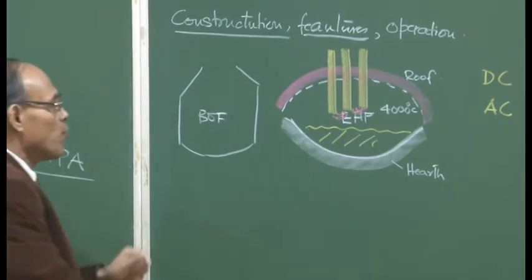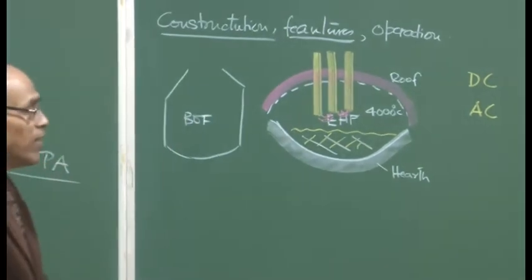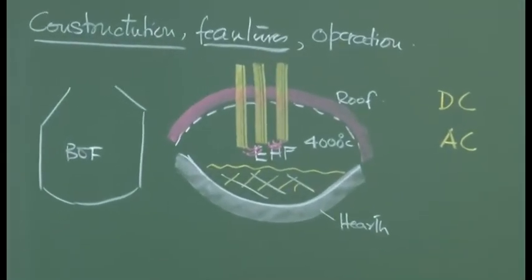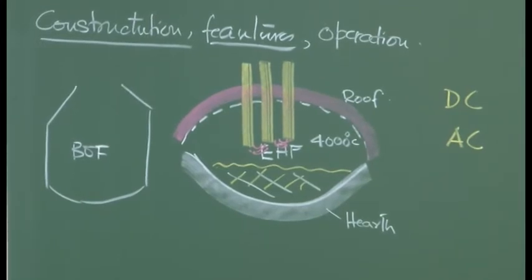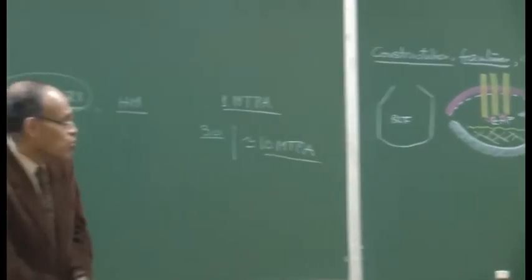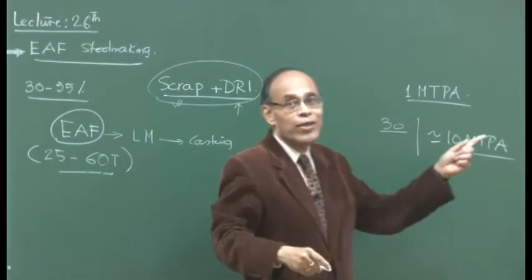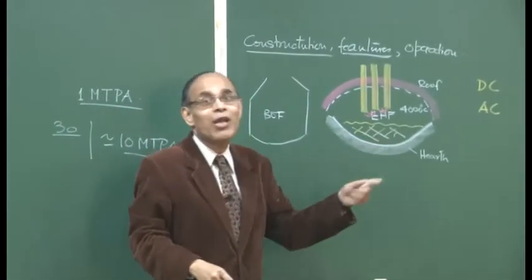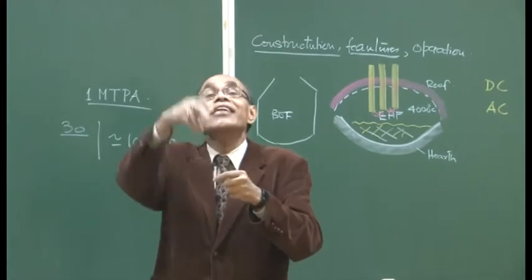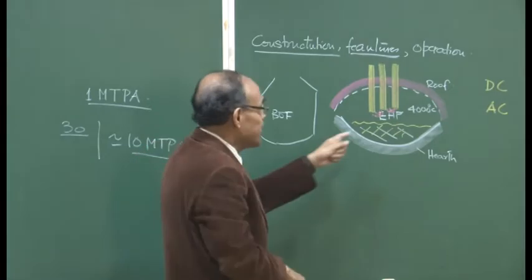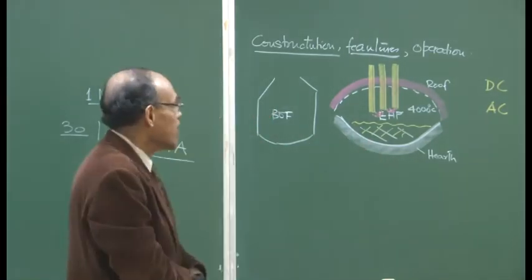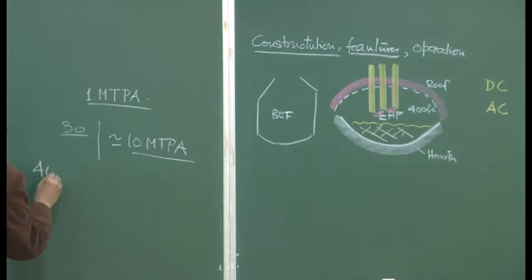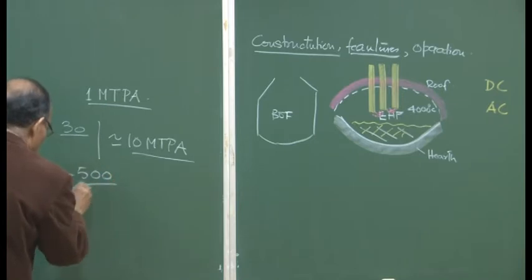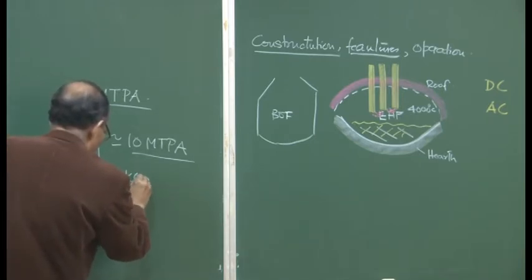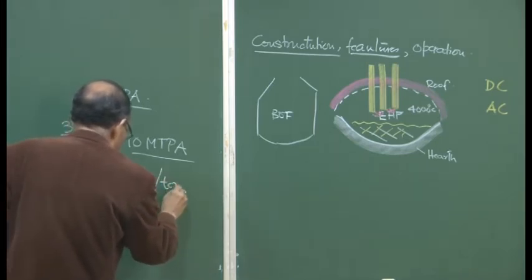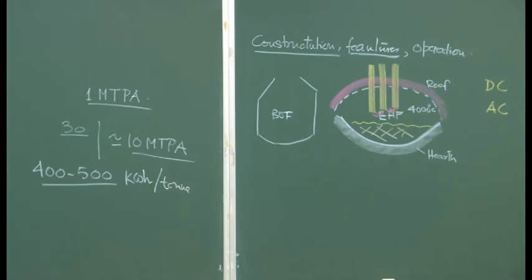But as such, in the beginning, when you have the solid scrap which is charged into the furnace, the scrap needs to be first heated to the melting temperature. That calculation you can very well do. So, if you take 20 tons of scrap, you multiply 20 tons of scrap by the specific heat of the scrap, multiplied by the temperature difference, since you are charging it at room temperature and then taking it to the melting temperature, you can calculate the heat. And depending on the scrap composition, we can say that 400 to 500 kilowatt hour per ton is consumed to just melt the material.